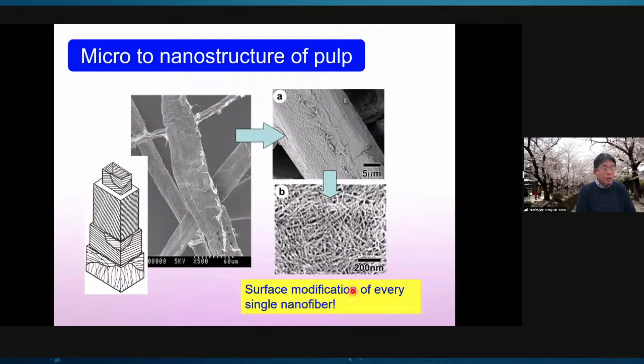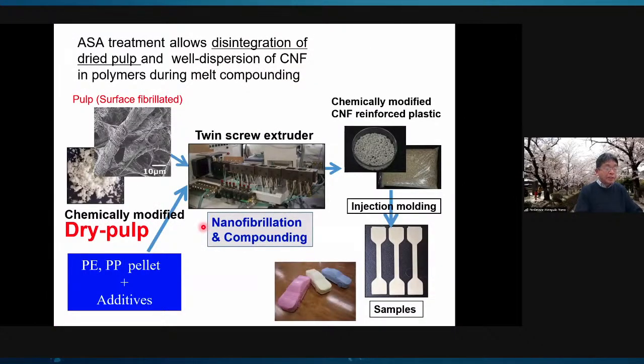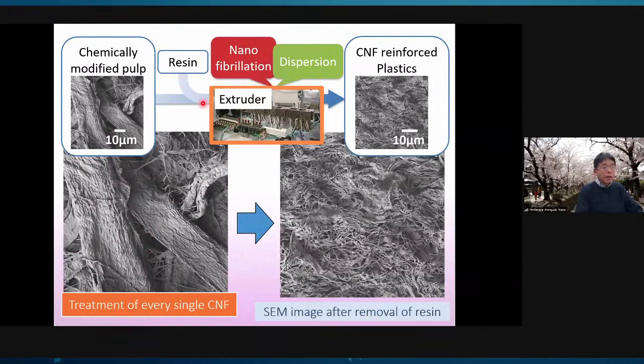Then we studied a process to reduce production cost and found that when we ASA treat the surface of every single cellulose nanofiber in pulp, the treatment allowed the disintegration of dried pulp and good dispersion of CNF in polymers during melt compounding. Here, you can see that dried pulp is nanofibrillated during melt compounding. Before it is put in the extruder, it is pulp. But after melt compounding, it becomes individualized cellulose nanofiber that reinforces polymers.